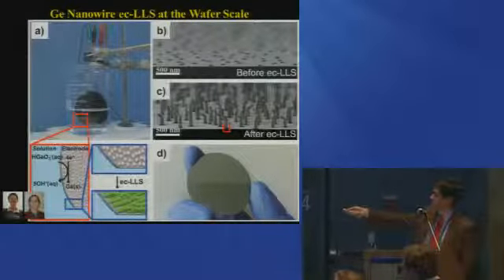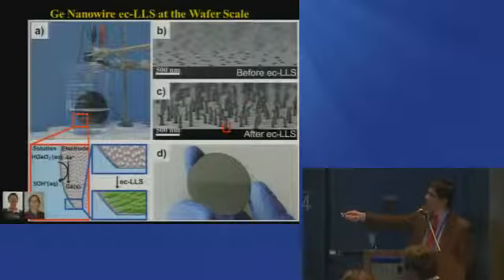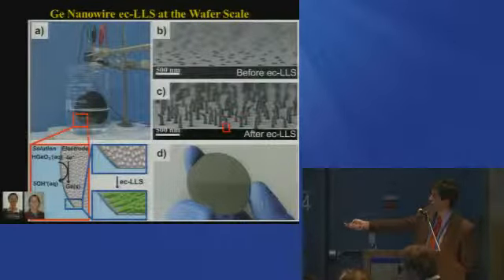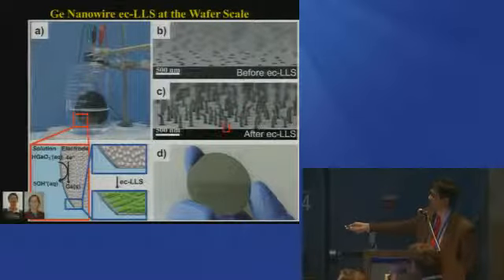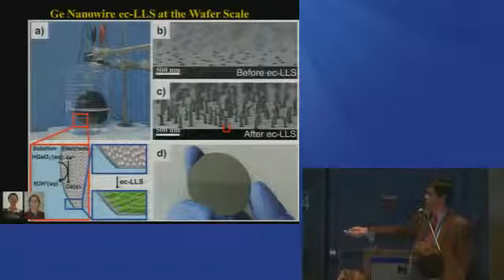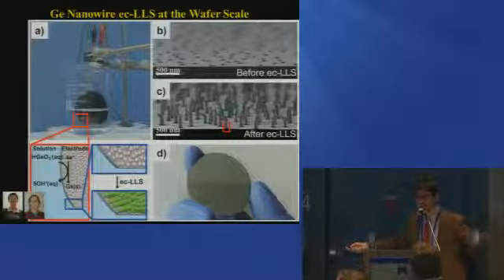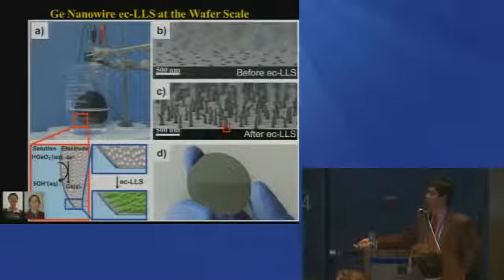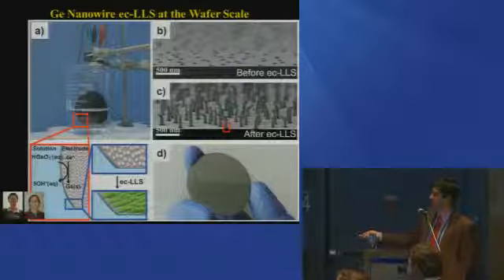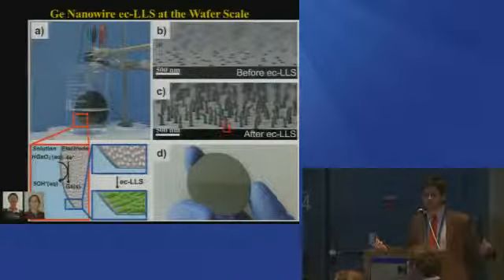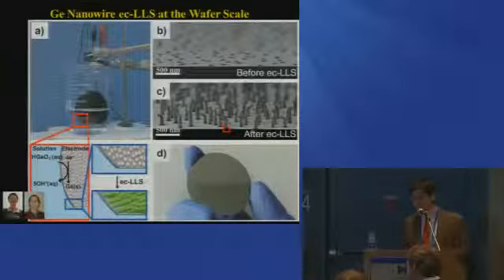So this can all be done with equipment that looks like this. The idea is that this platform is great for electrodeposition of single germanium nanowires, but in an array format. This is before and after this ec-LLS process, where each one of these nanodroplets is nucleating the growth of one crystalline germanium filament. You can do this on a large scale that's only limited by the source of your substrate, the size of your beaker, and maybe the ingenuity of the graduate students putting this together.